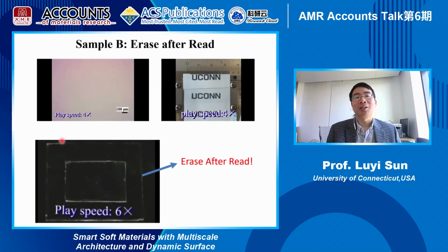Basically, this means that with water molecules, PVA can gradually lose mechanical strength and tend to be very soft. And to make this even more effective and sensitive, we use PVA with a very low molecular weight of 5,000. So with that, it loses mechanical strength and is flattened by the substrate.